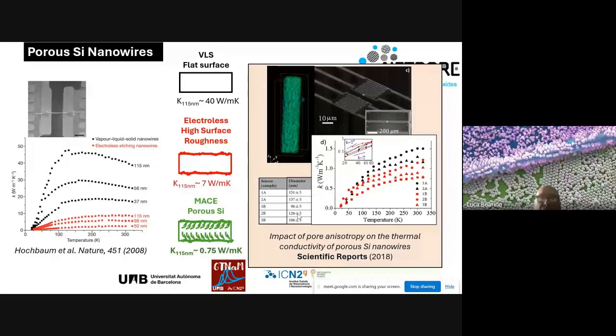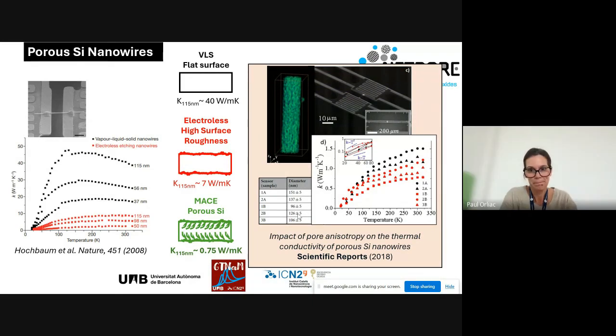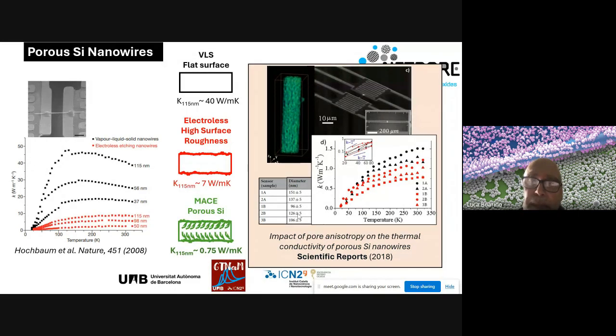Sure. Yeah, to complete the response, silicon is a very good mechanical material, okay? Porous silicon scales with the cube of porosity. So all the porous silicon is quite delicate, but at the same time, with nanowires, you can keep a very high aspect ratio. And metal-assisted etching is the only type of etching giving you aspect ratio over 200. There is no deep reactive ion etching that is capable of this. So we are doing, for example, this wire.